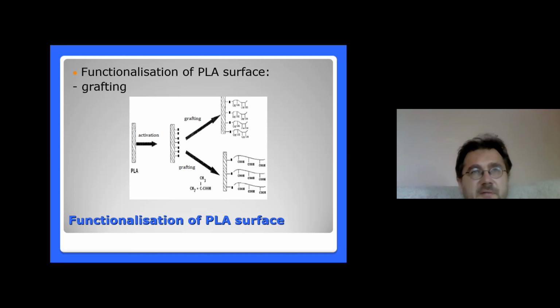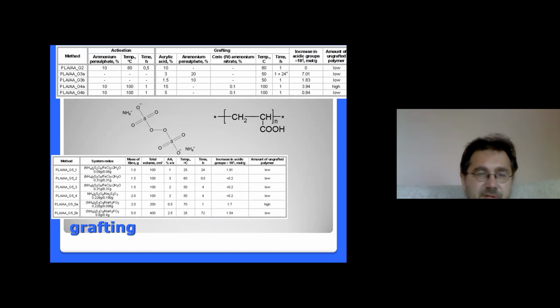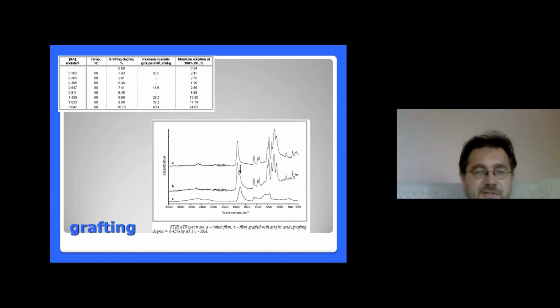The first way was grafting, because the external layer of the material can be strongly changed by grafting, because we have a connection here. This is grafting copolymerization, so we can connect different types of polymer by the main chemical bond. So it's very efficient, very easy. Typically, it's cheap, and we can introduce different polymers as an external layer. Most of our modifications concerned the introduction of polyacrylic acid. That was the basic material, and we changed the conditions of the grafted copolymerization, and we confirmed that it is possible, and the final effect strongly depends on the conditions of the procedure.